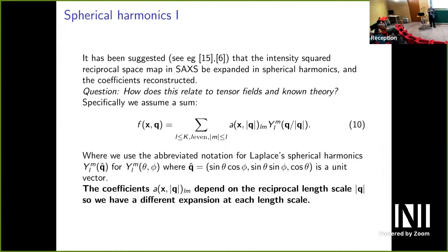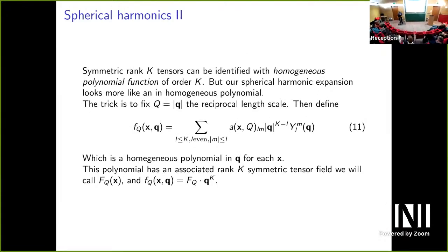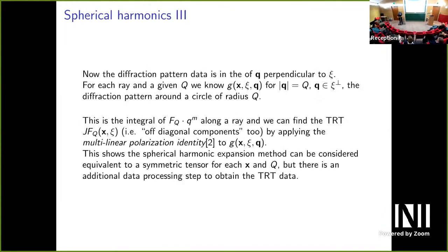And in fact, a lot of these anisotropic properties that are represented by rank 2 tensors, representing the fact that the material has some kind of orientation, that's actually a truncated spherical harmonic expansion, and maybe the other components are too small to measure, but it often comes down to that. Okay, so I guess that's all.